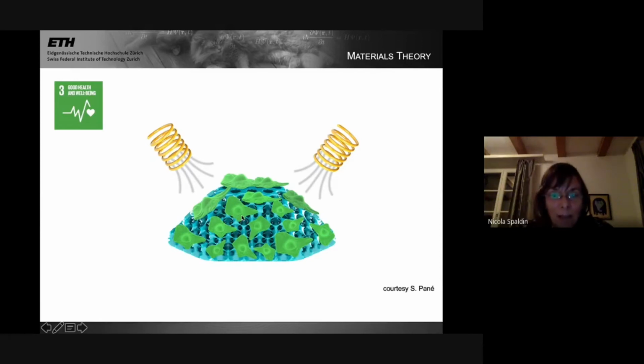biomedics in the audience. And again, what's being exploited here, this is in vitro, not in vivo, is the fact that the magnetic field will shake the bismuth ferrite, and the shaking promotes the growth of the osteoblast. So it's believed, for example, that bone growth is aided. Bone is a piezoelectric, it's like a ferroelectric. When we walk, the shock of the walking induces electric dipoles in the bone. And of course, if you're injured, you can't go and walk on your bone, but if you use the bismuth ferrite as a scaffold, you can apply a magnetic field to simulate the process of walking, again using the opposite direction, the magnetic field induced change of the electric dipole.